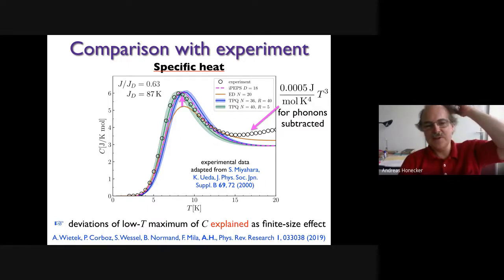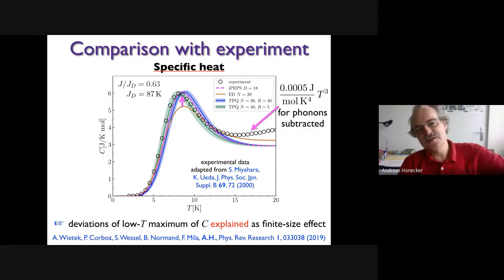But at high temperatures, there's a bit of an issue that you have phonons that you have to get rid of. So the deviation at high temperatures, I believe, comes from phonons. But you see here, there was a bit of deviation in the old data, so the 20-site system was not big enough. If you go to bigger systems, or the thermodynamic limit, meaning here 36 or 40 for that particular case, it seems to be sufficient. You get rid of this discrepancy and you get a perfect fit.